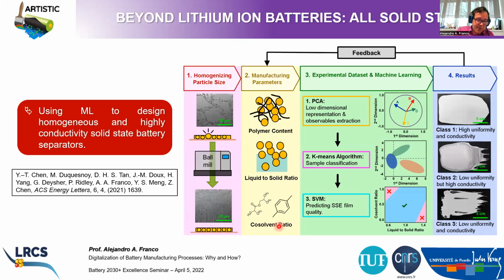This concept for casting, mixing, drying, and so on can also be extended to other battery technologies, and in particular solid-state batteries. And this is a work that we jointly published with the group of Shirley Meng last year, where we extend the methodology that we developed in the previous paper I showed in the previous slide to the concept of developing solid-state separators, right? And here we use as an input of the machine learning workflow the formulation, which is in this case controlled by the amount of polymer that you put in your slurry, the liquid to solid ratio, the co-solvent ratio, and so on and so forth. And then we derive a model, which is also a supervised model, which is able to predict under which formulations and under which casting conditions you will get solid-state separators with high uniformity and high conductivity, right?